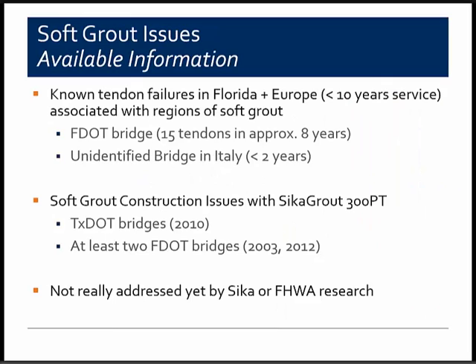But unlike the chloride content issue, soft grout problems have been linked to tendon failures and corrosion problems on several existing bridges, and the problems manifested quite quickly. As Brian noted, multiple failed tendons were found on an 8-year-old bridge in Florida, and failed tendons have also been reported on a 2-year-old bridge, actually less than 2 years old, in Europe. In both cases, failure locations were correlated with regions of soft grout. Also, the formation of soft grout has been noted during or following construction on several bridges where SikaGrout 300PT was used, including bridges in Texas, as Brian mentioned, and several in Florida, including some product that I believe was not from the Marion, Ohio facility.